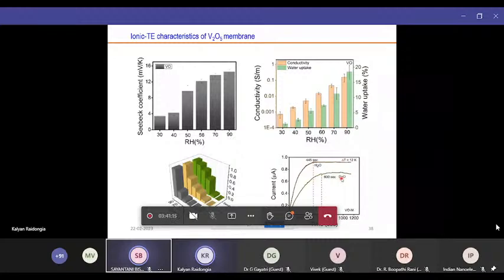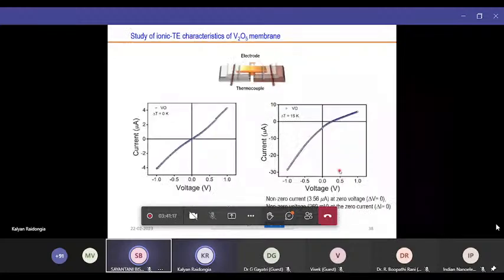This is because H2O is changed to D2O, and D2O is heavier than H2O, so we see this difference. And similarly, once we apply the temperature difference, the ions are supposed to move from hot zone to cold zone. Now, if you do an IV curve, we can see this IV curve is not going through the origin. We have a net non-zero current at zero voltage, as well as a non-zero voltage at zero current, which is another proof that ions are actually moving from one zone to another zone.